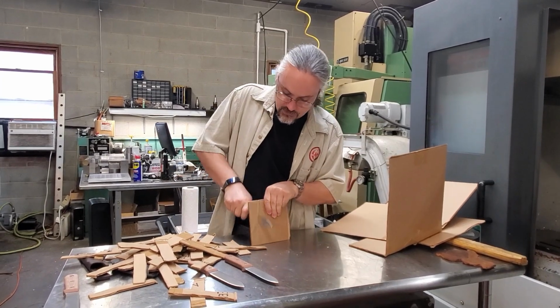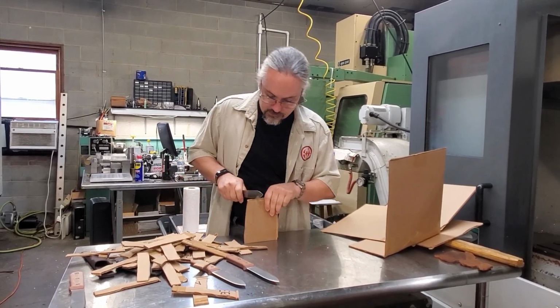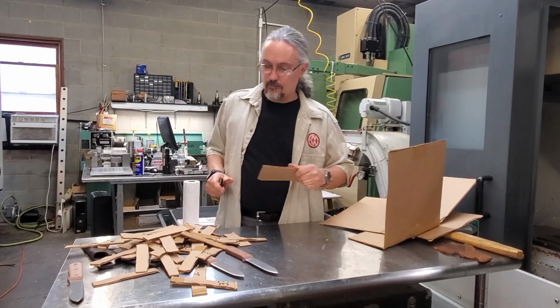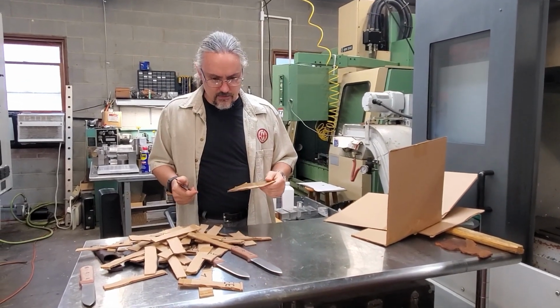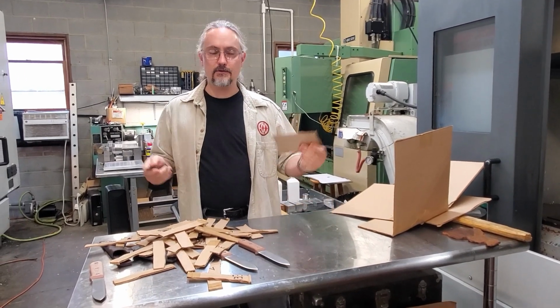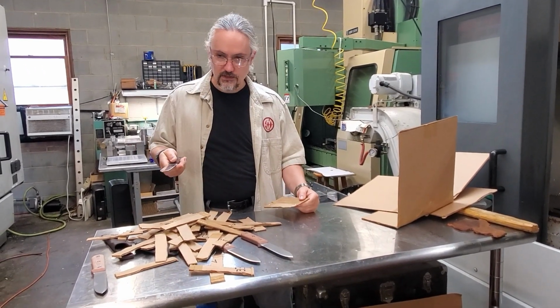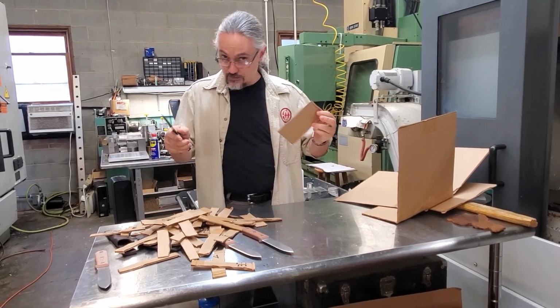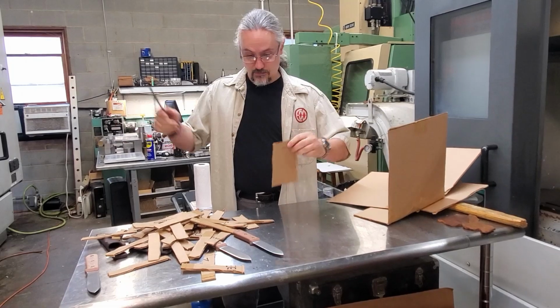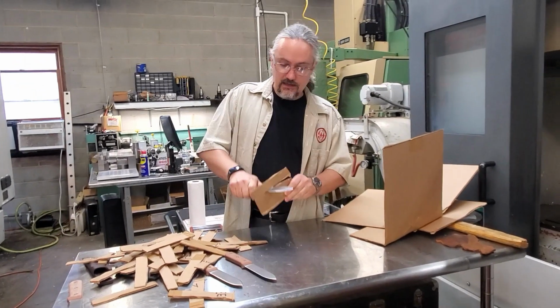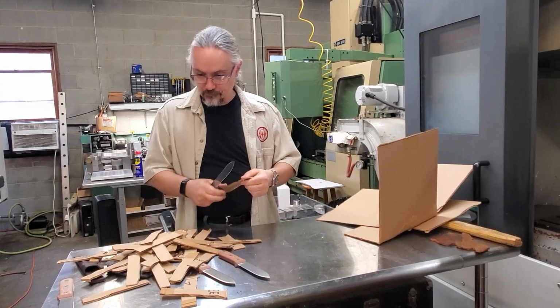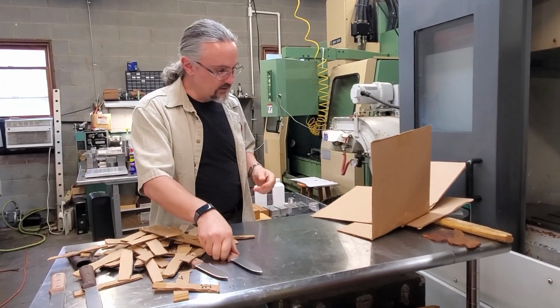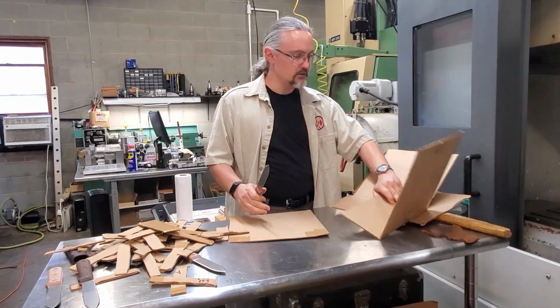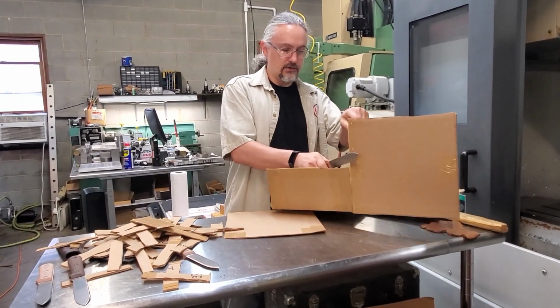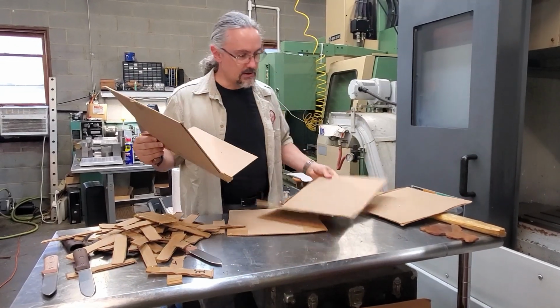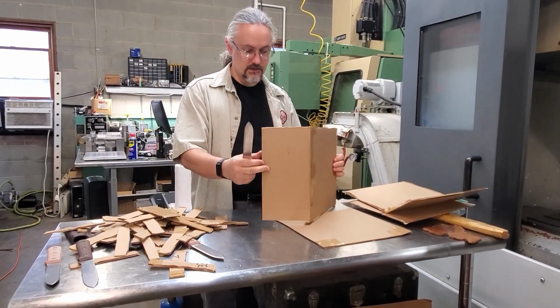And in fact, this is a problem you can run into with heat treaters that aren't really set up and experienced doing knives: they can have the temperature in their oven reverse. They're using these vacuum ovens, and you can get a pretty good quench, and so far so good. Then you leave it in the oven, and the oven's got some thermal mass, and the temperature reverses, and you'll stabilize some retained austenite. So there's a lot of pitfalls, a lot of things that can go wrong. So if you're using one of the low temp tweaks, you need to make sure that your heat treater is doing it right.